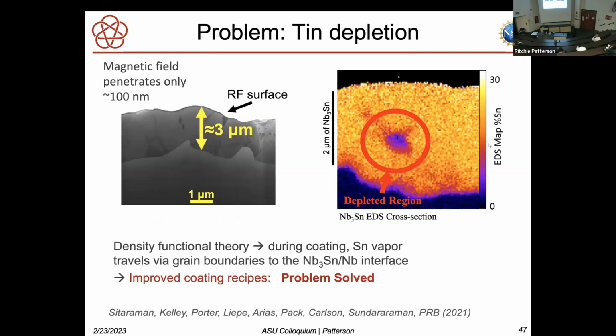And if you look at surfaces that you prepare, we found that initially we had lots of depleted regions. That was really bad. And we used density functional theory to understand the growth process, how the tin was migrating through the niobium. And that led to changes in our growth. And that has now solved this problem. We now are able to produce good niobium-3 tin surfaces without these kinds of depletion regions.